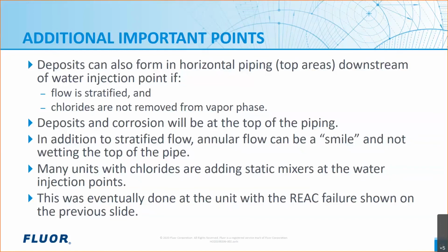And another warning is that even if your flow modeling has said that it's going to be annular flow, which sounds much better than stratified flow, sometimes annular flow is only a smile. It doesn't fully go around to merge at the top of the pipe, and so it's not wetting that top of the pipe. And in that case, you can still have these deposits form and lead to the corrosion. So at this point, many units with chlorides are adding static mixers at the water injection points, just to help ensure that these horizontal runs and such don't have this risk downstream of the water injection point. And that unit where we looked at the failures, that was the solution for that unit. It eventually added a static mixer at the water injection point. And then most of these problems have been solved.